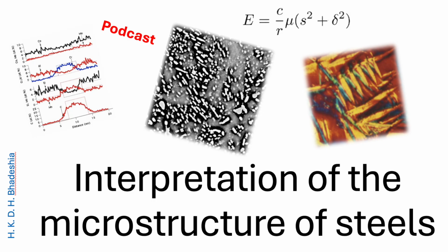The big substitutional alloy atoms like manganese or nickel, they're too slow. They're stuck. They have to move together, disciplined, like the displacive path. Okay. But the small interstitial carbon atoms, they do diffuse and partition, just like the reconstructive path. So it gets the high strain energy of displacement, but its speed is throttled by carbon diffusion.